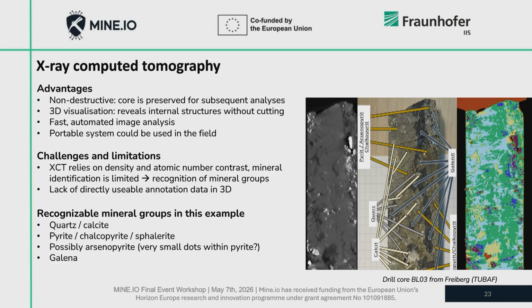Yeah, so in this case we had a drill core from Freiberg, and we recognized 4 different mineral groups. So it was quartz and calcite forming one group, pyrite, chalcopyrite, and sphalerite as the second group, arsenopyrite, and galena. And on the right side you can see the images. So the black and white image is the raw X-ray computed tomography image. So this is just a 2D slice of a 3D data set. And then on the very far right side you can see the segmented image where the colors are showing the different mineral groups in the segmented image.